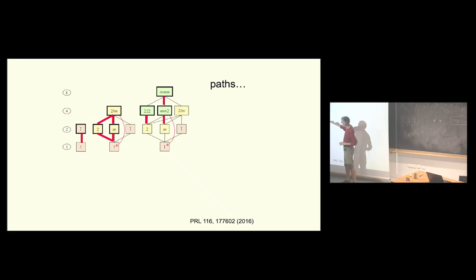But the species is something which goes from a higher group to a lower group, and there could be some intermediate. So for example, a species is from 2/m to 1. So you lose all symmetry elements except for the identity. This is a species. You go from 2/m to m. This is also a species. Yeah? So it's the higher symmetry and lower symmetry, just two groups.